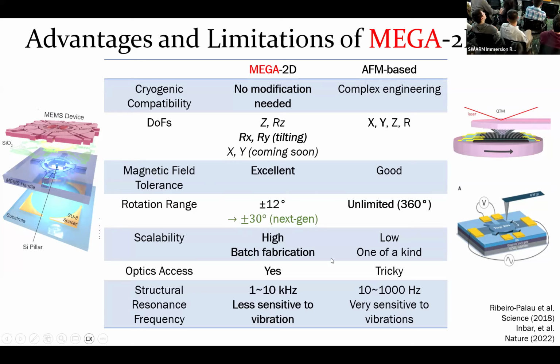But of course, it would be nice if it could rotate freely, especially since these 2D materials usually have a hexagonal structure, right? If you can rotate 60 degrees, then you can cover the entire parameter space for studying these materials. And we are right now working on the next generation of this device, which will allow us to twist plus or minus 30 degrees, which will be 60 degrees in total.